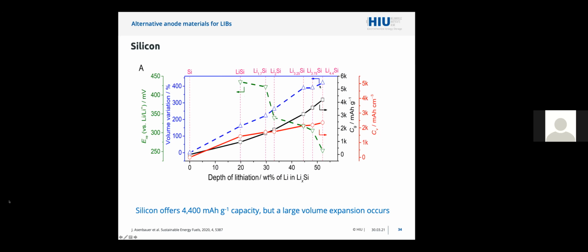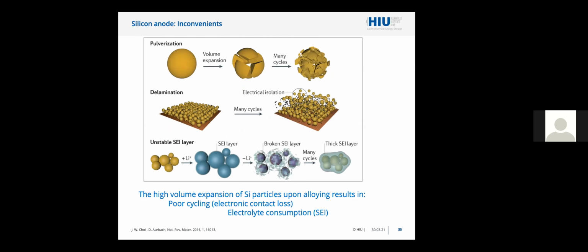And this blue curve, all of you know about this: the volume of silicon increases enormously upon alloying, or uptaking, of lithium. And this is leading to what is well known as the pulverization of the silicon particles. They tend to break because of the stress induced by the volume change, and the coating tends to delaminate, always because of this volume change. And this is leading to poor cycling, as well as, very importantly, electrolyte consumption. Why is that? Because the pulverization breaks the SEI, creates new active surface, and then new SEI is reformed. And this in the long term is leading to large electrolyte consumption.